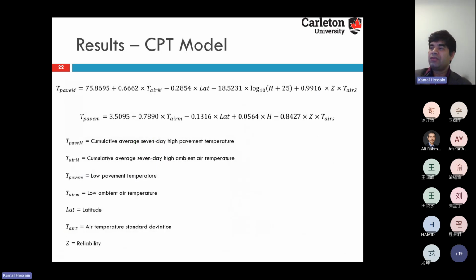So just one second, I wanted to show the model first. This is the Canada-wide model for pavement temperature, for the high temperature and low temperature scenarios. As you can see, T pave M is the cumulative average 7-day high pavement temperature, and T pave small m is the low pavement temperature model. It's the Canada-wide model using high air temperature, pavement depth, some statistical variables, and also latitude in the regression model that we calibrated using the Canadian database.